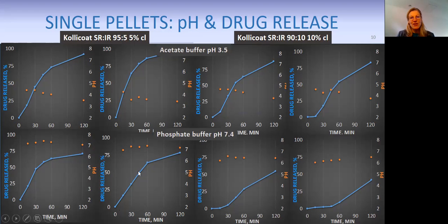The second pellet observed from this very same batch of pellets has even shown a different drug release. You can see that it's going up steadily. We finish with about 75% of drug released, but also the pH in this very same pellet goes rather towards 7, not 7.4. With the 90:10 blend-coated pellets, the difference is even more significant.